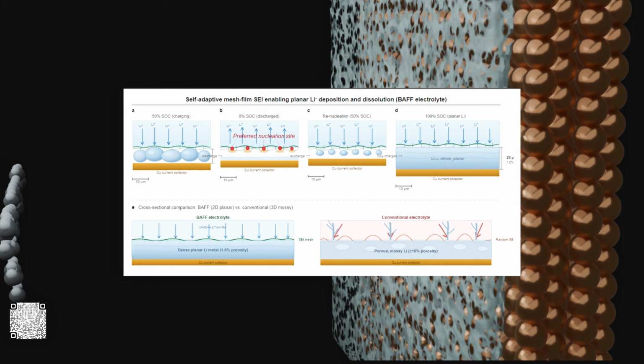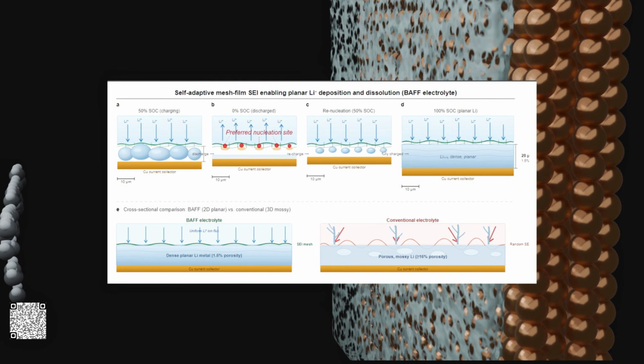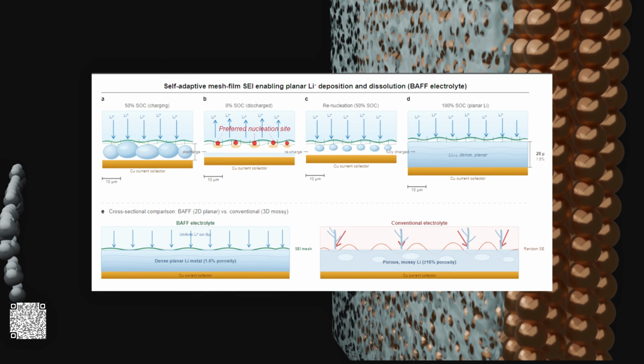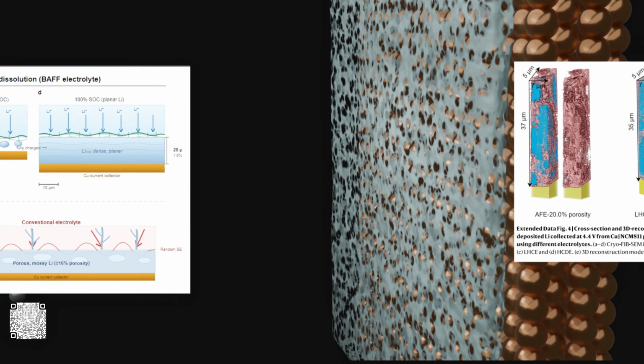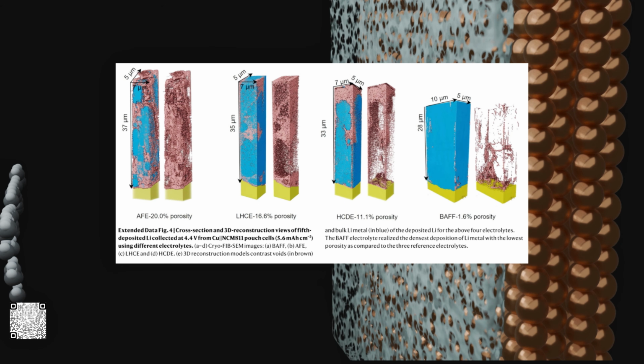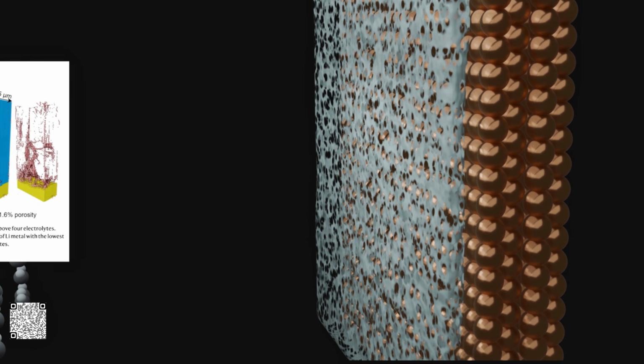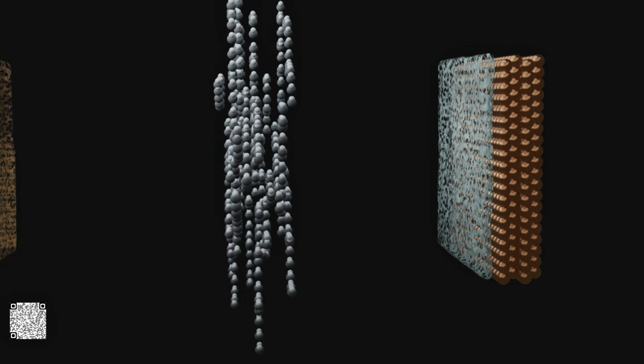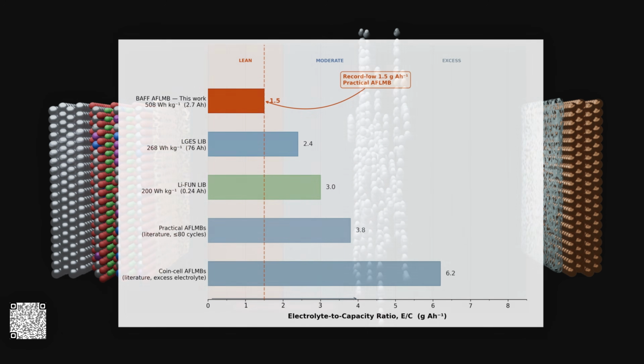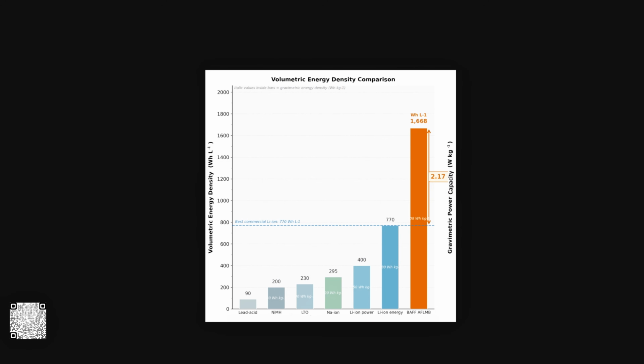This mesh creates preferred nucleation sites, so that on the next charge, the lithium grows back exactly where it was. Cryo-FIB-SEM shows the result, a deposit with only 1.6% porosity. At the cell level, this means we can finally use a lean electrolyte-to-capacity ratio of just 1.5 grams per amp hour. This 2.7 amp hour pouch cell hits a volumetric energy density of